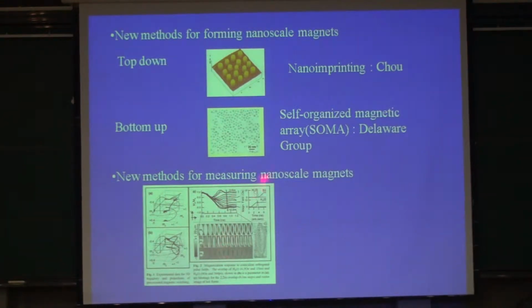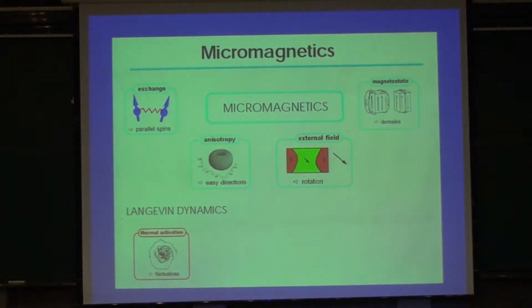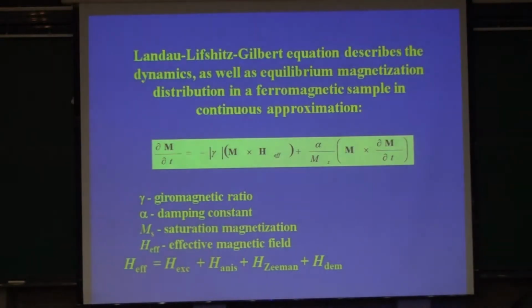But anyway, at that time a lot of new methods were also invented to measure nano scale magnetic response. The very powerful, semi-classical way to analyze nano magnetism and micromagnetism is that we include the exchange energy, anisotropy energy, the external field, and also the magnetostatic energy, also including the thermal effects, Langevin dynamics, to analyze this.